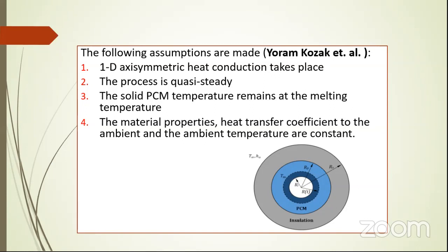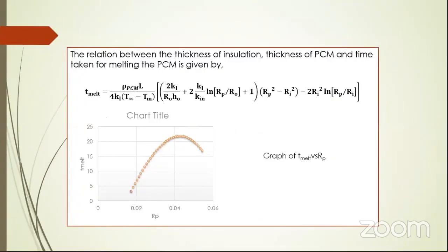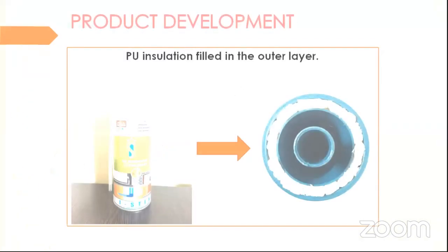That is quasi-steady state. The solid PCM temperature remains at the melting temperature. The material properties, heat transfer coefficients to the ambient and the ambient temperature are constant. So these are some assumptions we took while making the model of that flask. And this is the relation between the thickness of insulation and the thickness of PCM. So what's the thickness of insulation, and what's the thickness of PCM material we placed, and how much time is taken for melting the PCM. So we made these 3 relations by using this graph.